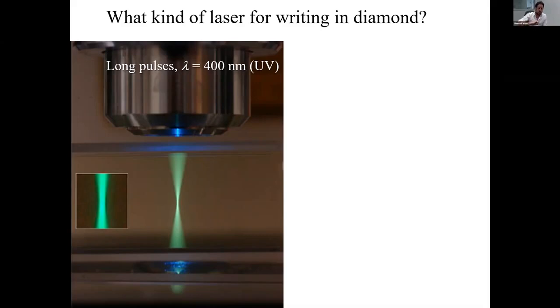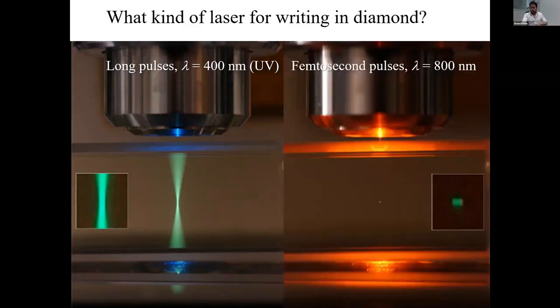So here in this case, we're essentially using a very short wavelength of light to excite the electrons from the valence to the conduction band. This is much the same case in glasses. Transparent glasses, and also diamond. So what we propose to use are femtosecond laser pulses. And here we're typically using femtosecond lasers in the near infrared. Here's an example of a Ti:sapphire laser coming in again from the top, going through a focusing lens. And what you can see here is much more precise, it's very hard to see, but you can see this very precise green emission just at the focal volume, where you have an intensity over a certain threshold intensity to drive nonlinear absorption, as opposed to linear absorption on the left.